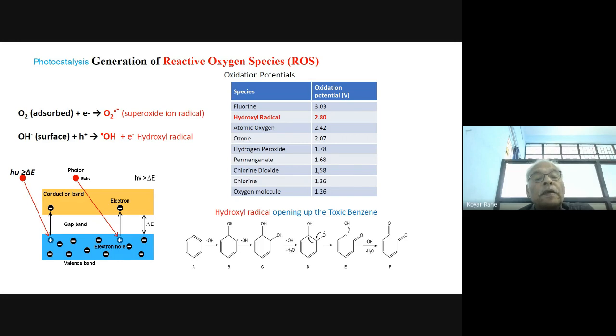And if you see the various oxidation potentials of the various species which are used in oxidation, fluorine has the highest oxidation potential, atomic oxygen is around 2.4, ozone has 2.07, hydrogen peroxide is around 1.7, permanganate, which is normally used, 1.68, chlorine is just 1.36, and the oxygen molecule has a potential of 1.26. Considering all those things, fluorine is the best oxidant, with very good potential. But the hydroxyl radical thus produced on the semiconductor is equally very close to fluorine and better than all other